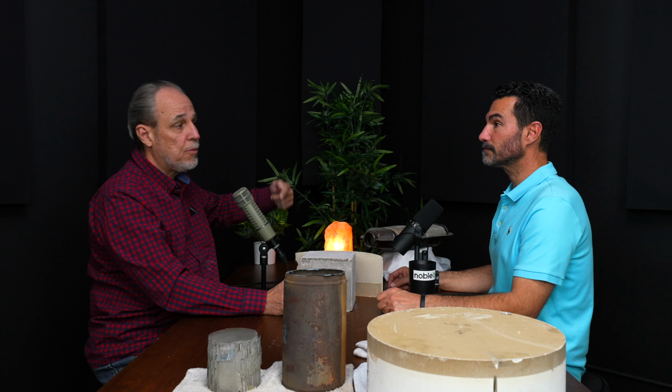Smelter capacities need to increase to handle the volume of materials that are coming in the next 20, 25 years from catalyst. That's number one. Number two, they need to increase beyond the ounces that they have to recover because they have to wash their slags. They have to re-melt their slags to get from their 98% recovery up to their 99% recovery. They have to continually wash slags to do that, which is more energy, more carbon footprint, all of that.